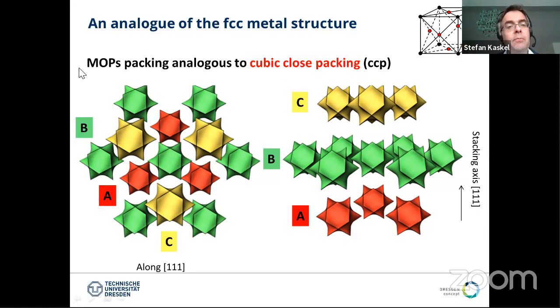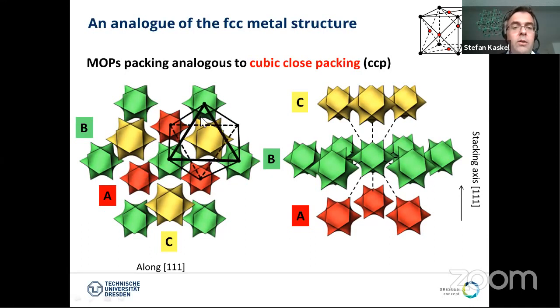And essentially here you have MOPs packing in a CCP fashion. And the students in the first semester, we teach them that this is an ABC packing basically. But what is interesting, when you connect these spheres, so in the metal, of course, these are just atoms, but here we connect these MOPs with the biphenyl linkers, for example, and then we create the voids in between the spheres, like in the CCP packing. So there are tetrahedral voids that you can see here, and there are also octahedral voids that you can see here from the ABC packing in between the layers, basically.